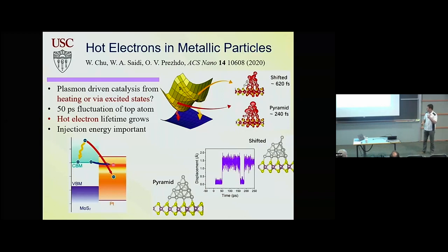It's still true, but I'm saying on top of that, you have very large fluctuations. Even if the trap state is shallow, it has to be within kT for the charges to escape. But 0.1 eV is already more than kT, and you definitely have trap states that are 0.1 eV inside, but they fluctuate. Thank you.